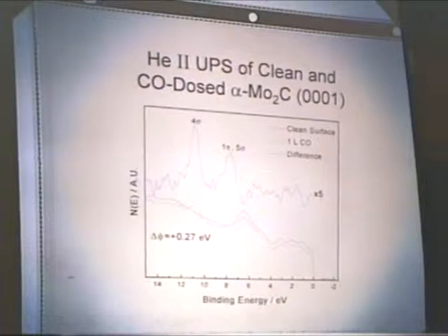The fact that we do not see a 5 sigma peak in this region is typically interpreted as being an overlapping peak with the 1 pi. This is a result of a stabilization in the 5 sigma energy because the carbon is participating in a bond with the surface. The conclusion then is that carbon is bonded down to the surface, as you would expect for CO chemisorption on metals.